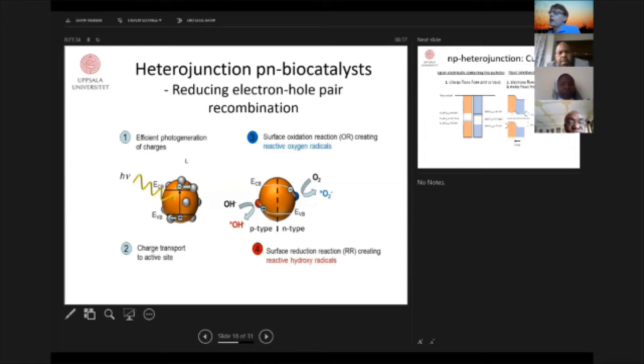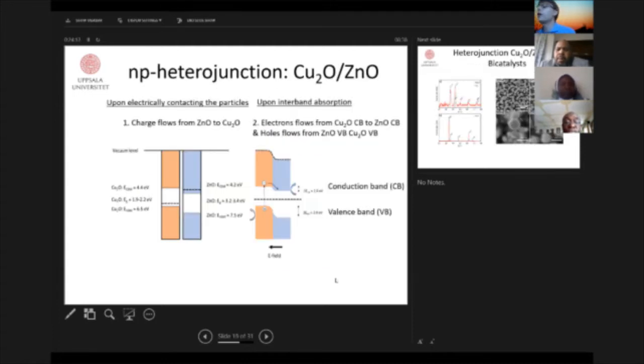This electron hole pair wants to recombine. So one way to prevent that is to use the semiconductor physics concept of placing a p-type and an n-type material close to each other and let the electron hole pair separate across a boundary where you have electrical contact between the two materials, p-type and n-type. And this is what I will discuss now. I will show one example where we place copper and zinc together and see if we can get this to work. Then you do the oxidation reactions on the p-type and the reduction on the n-type.